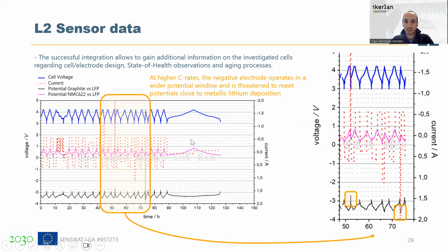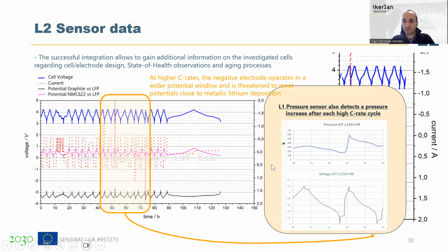We can also detect that at higher C rates, the negative electrode, in this case in the opposite way, operates in a wider potential window. As you can see here with a 3C discharge and here at a 3C charge, it goes above and below the normal operation window of the anode, and this means that we can have some metallic lithium deposition in those points.